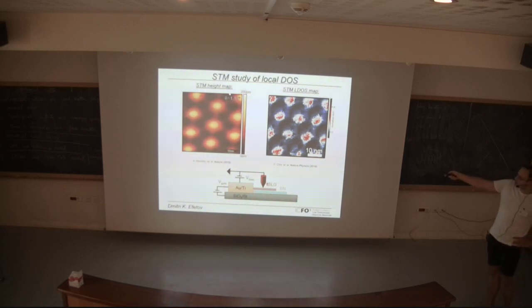This is, for example, a typical STM height map which they can perform on twisted bilayer graphene. They really find that these AA lattice sites have enhanced conductivity compared to the AB lattice sites. Of course, they can also take spectra and measure the local density of states in the system. Indeed, they find that in these AA lattice sites they have enhanced local density of states, in a similar picture to what I explained in the beginning. So really, this whole twisted bilayer graphene breaks down into these Moiré unit cells with very high local density of states.